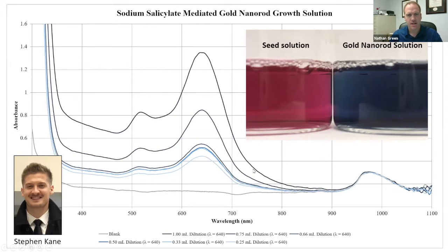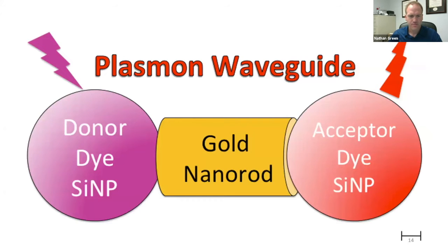He was making a concentration curve here to figure out the concentration. So that's why these are just increasingly concentrated samples of the same gold nanorod solution. But you can see this nice blue that you get from this. That's when you have a longitudinal plasmon about 630 or so, you see this blue solution. So it's always really obvious when we make the particles well, because it's really hard to make gold look like it's blue. But we've gotten quite good at it.